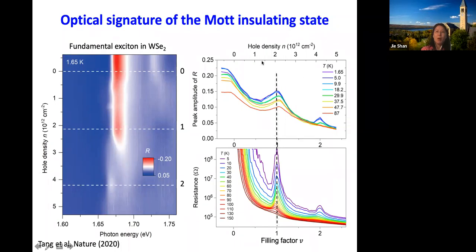In this plot, we show the peak amplitude of the reflectance as a function of filling. And you can clearly see that there is increased reflectivity at full filling and half filling. The way you can naively understand this is that those are insulating states, so excitons are screened less, and that's why they have higher oscillator strength.